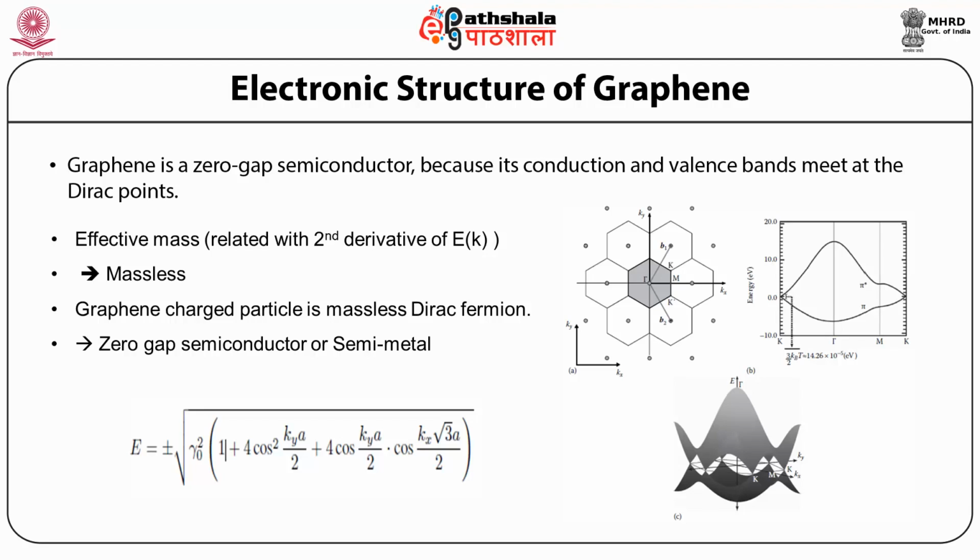By contrast, for a traditional semiconductor, the primary point of interest is generally the gamma point, where momentum is 0. Electrons propagating through graphene's honeycomb lattice effectively lose their mass, producing quasi-particles that are described by a 2D analog of the Dirac equation rather than the Schrodinger equation of spin half particles. This is a new feature in graphene systems.